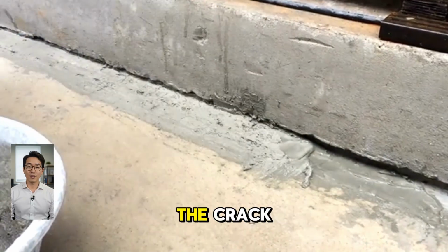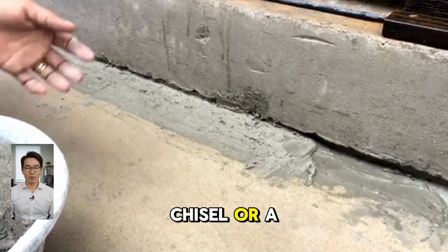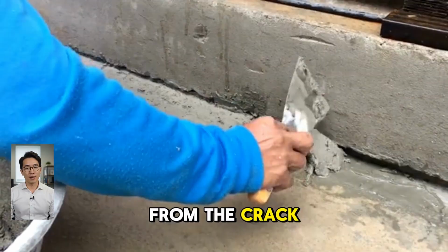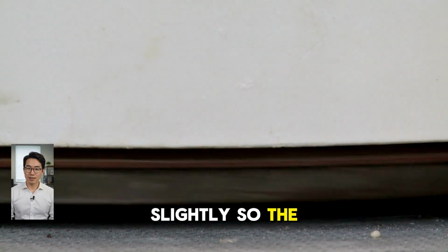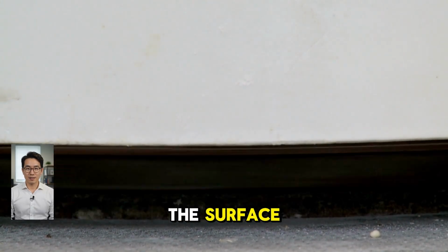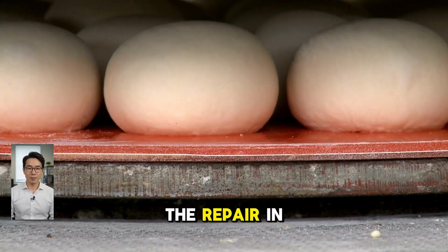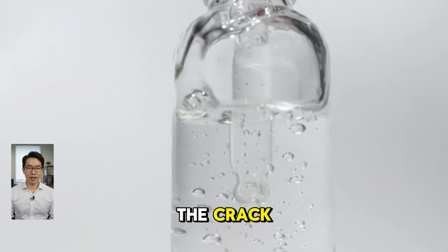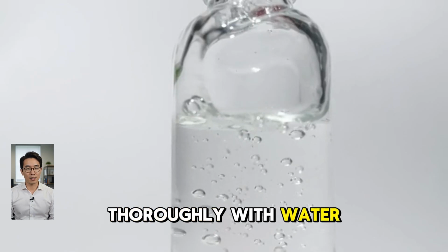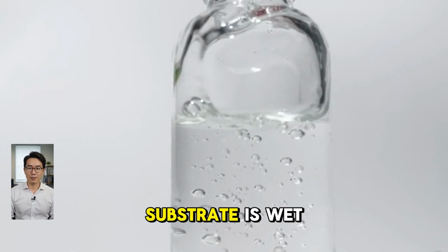Step 1, prepare the crack. Using a cold chisel or a wire brush, clean loose material from the crack. Undercut the edges slightly so the crack is wider at the interior than at the surface. This creates a keyway that locks the repair in place. Step 2, wet the crack. Dampen the interior thoroughly with water. Hydraulic cement works best when the substrate is wet.